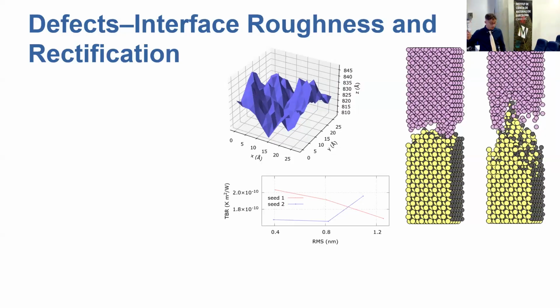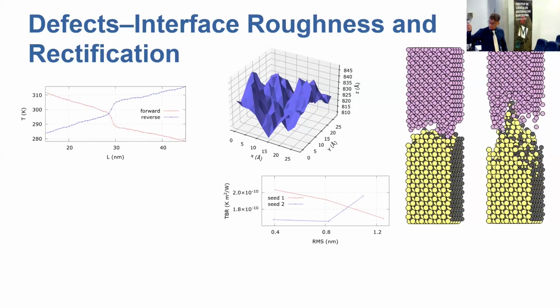Then we studied rectification. Rectification has to do with the fact that since the system is non-homogeneous, when we swap the 2 temperatures, we will observe in general a thermal conductivity and a thermal boundary resistance which is not the same. Here you can see the temperature profiles in the forward and reverse configuration, where you can appreciate that even if the conditions at the ends of the junctions are perfectly symmetrical, the temperature profile is not symmetrical with respect to the interface zone.